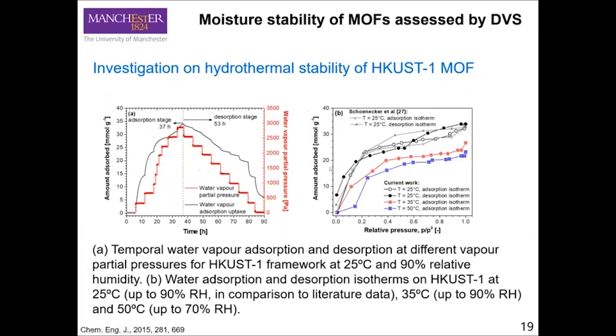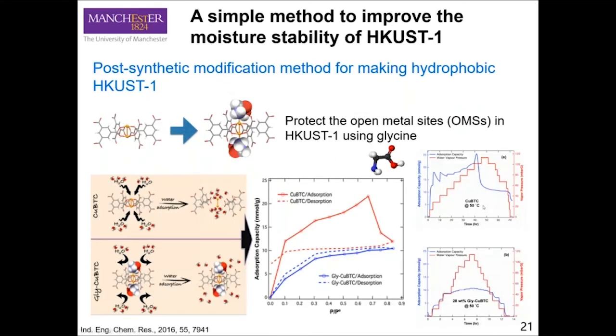If we go back to previous slides, you can see that at roughly 25 degrees Celsius, room temperature, the MOF is doing okay. We have more or less full adsorption and full desorption, but still some water kept in the framework. But at relatively higher temperature, you can see the spikes over here indicating the framework has been damaged. And this is permanent. If we keep increasing the adsorption time to 40 hours, we see a sudden drop of the mass, which means the framework is damaged and the vapor has been released, causing the loss of mass of the adsorbent. Yeah, that's the reason.